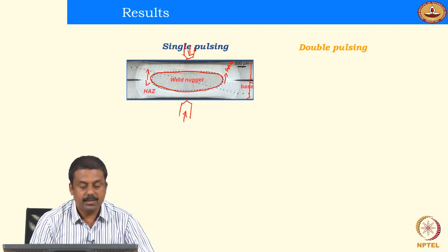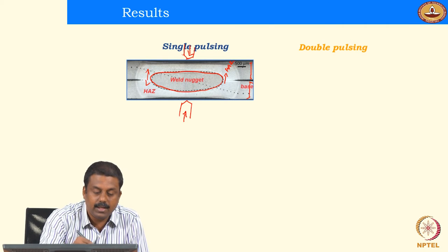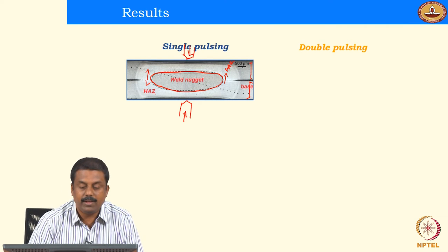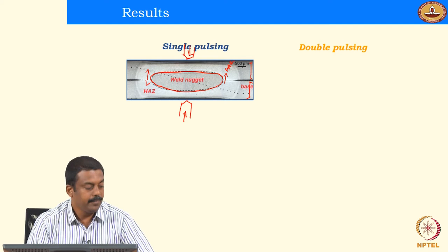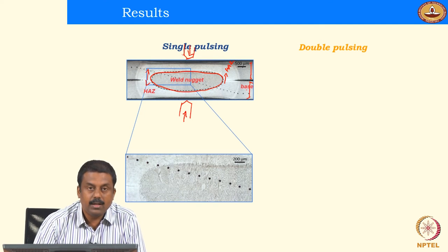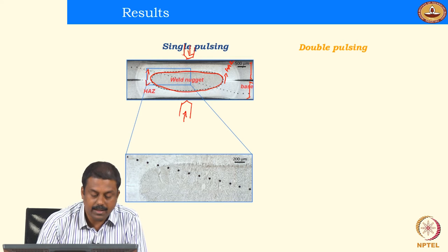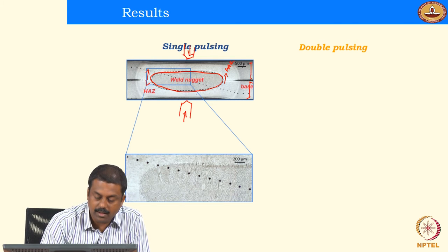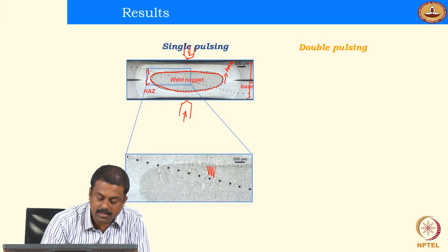And during this first single pulsing, what happens? So, this is a weld nugget and this is the HAZ, what you see over here, and this is the base material. And if you look at somewhat higher magnification, you see very clearly the columnar grains which are actually grown from the fusion boundary towards the weld center line.